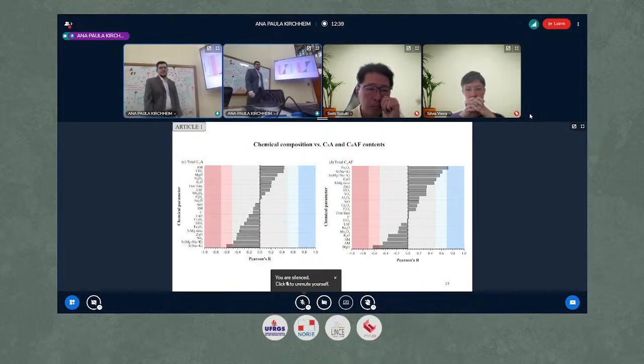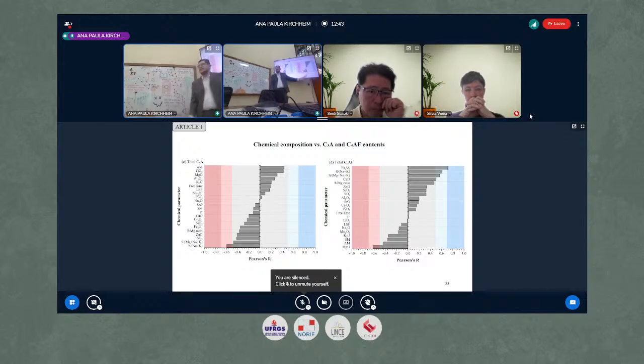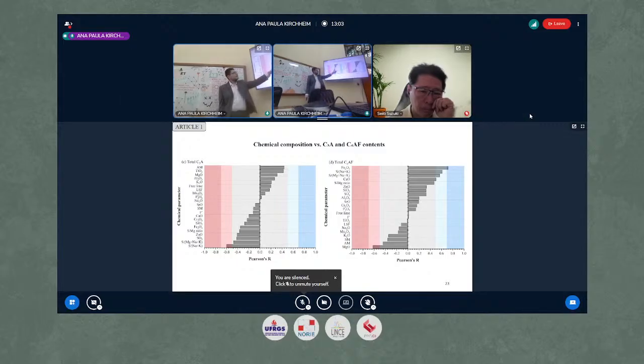Here in C3A and C4AF, for C4AF, as expected, the main influence was iron, but we also see some influence of sulfate again and alkalis. If we increase sulfate, we will form more C4AF and less C3A, while increasing alkalis, we increase C3A and decrease C4AF.